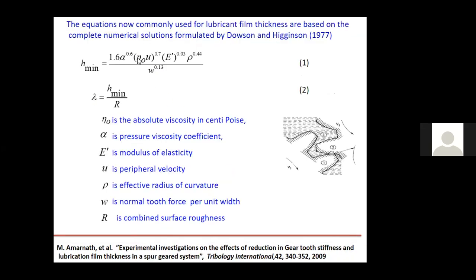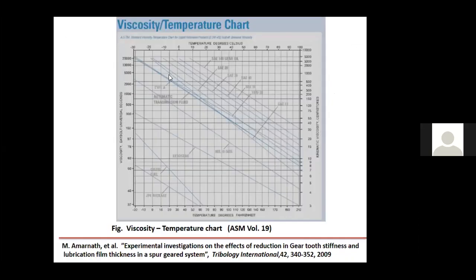To estimate the viscosity, it is not possible to use a viscometer in the gearbox housing, right? So just to get the temperature, you can use the ASTM chart, I mean the viscosity temperature chart developed by ASTM. Then you will get the change in viscosity based on the oil grade with respect to temperature. Here as temperature increases, SAE 40 oil was used here, so its viscosity is decreasing in this fashion. You can use the ASTM viscosity temperature chart to get the details of viscosity with respect to temperature.